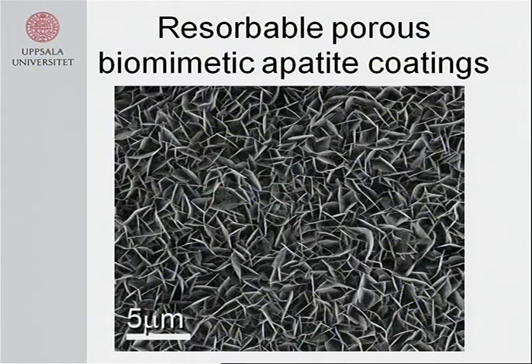And this is how it could look on top of a metal implant. These sheets are hydroxyapatite grains, and the thickness of these coatings is between, let's say, 100 nanometers up to several microns, up to 10 microns. And it has a very high surface area. We have been testing this for delivery of bisphosphonates and delivery of BMP2s, and also slow release of antibiotics.